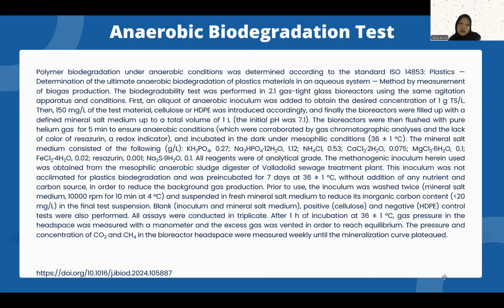Gas pressure in the headspace was measured with a manometer, and the excess gas was vented in order to reach equilibrium. This pressure and the concentration of carbon dioxide and methane in the bioreactor headspace were measured weekly until the mineralization curve plateaued.